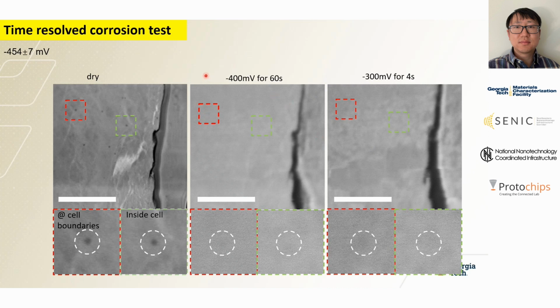So this is for the time-resolved corrosion test. After we maximize the flow rate, the OCP, the open circuit potential, increased to minus 454 plus or minus 7 millivolts. And this is the piece of sample before we immerse it in the solution. I selected 2 representative areas shown here.